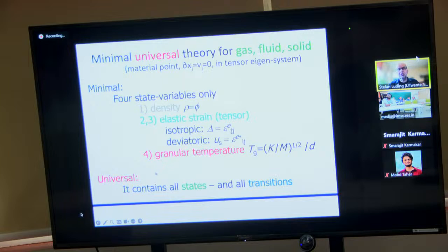That is 4, in my opinion, and that can be discussed, but I think 4 is the minimum you need. The first one is density, classical density, volume fraction. Density and volume fraction are for me synonyms; I will use one or the other. And then we have elastic strain. We could use the elastic stress, but I use elastic strain, inspired by Mario Liu, who developed the GSH. If you talk strain or stress, then you have two possibilities. The first is isotropic: not sheared, not shape changing, but volume changing. The second is deviatoric, like shear: shape change, no volume change. You can split strain or stress into isotropic and deviatoric parts, and those are the two state variables. In 2 dimensions, that's it. In 3 dimensions, you need a third one, but I skipped that one.